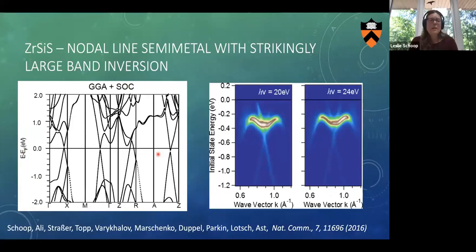And so if you calculate the electronic band structure of this material, you get these beautiful band crossings. And I'm not sure if it's still the case, but for a really, really long time, this was the topological semimetal with the largest band inversion in energy, like this goes from -2 to 2 eV here in some areas, with the exception of graphene. So you get a beautiful band structure. It's a bit different from graphene because it crosses more often, and that's why it's called a nodal line semimetal, and that's related to the symmetry of having a square net rather than a honeycomb. But this band structure does not only exist in DFT, it has been proven with ARPES and transport and all the other methods many times.